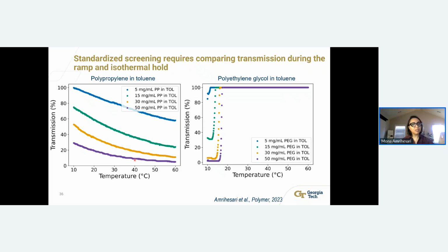So transmissivity is catching up with the changes in temperature as the polymer solution is going from one phase to the other. Versus on the right, for polyethylene glycol, we see a little bit of sharp drop, meaning that the kinetic is not as fast as the other system.